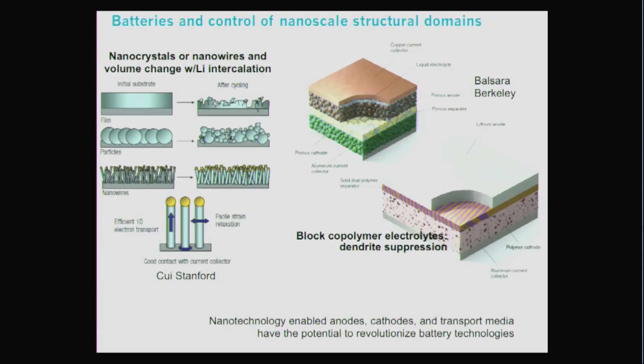So Yi Cui, who's here at Stanford, realized that a fundamental scaling law of nanomaterials is that they can undergo these types of transformations, and therefore he took nanowires and showed that they could be lithiated, silicon nanowires, that they could be lithiated, and they could withstand the volume change without cracking and falling apart in the way that a conventional battery might. This is an example of finding how a scaling law in nanoscience then eventually finds its way into the design of a new kind of battery. And in fact, nanotechnology-enabled anodes, cathodes, and even transport media are going to really change battery technologies in dramatic ways. That's built off of that finer understanding of the scaling laws that underlies it.